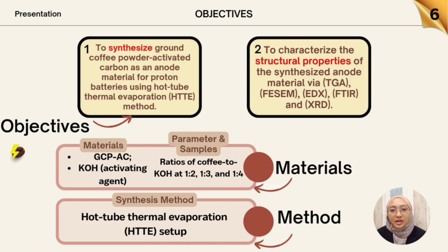And second, to characterize the structural properties of the synthesized anode material via TGA, FESEM, EDX, FTIR, and XRD. We experimented with three coffee to KOH ratios, which are 1:2, 1:3, and 1:4, using the HTTE method to determine which ratio provides the best balance for proton battery applications.